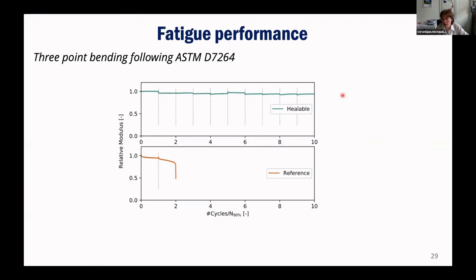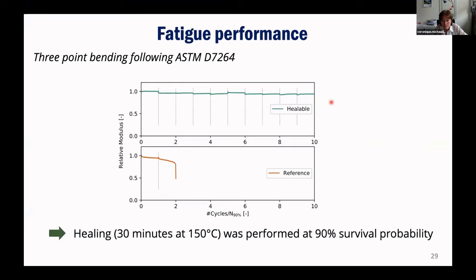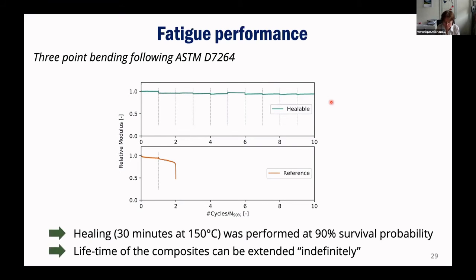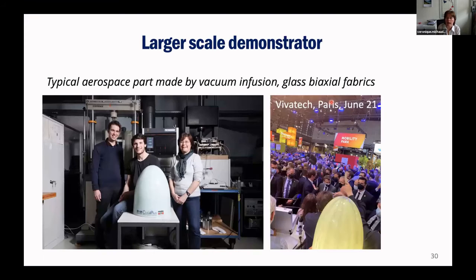And we did it up to 10 times, and then we got tired, we decided this was enough. But we had like an infinite lifetime, at least, by performing this 30 minutes intervention every so many cycles. So we saw that this was quite promising. And then we went on, we also did some prototypes,